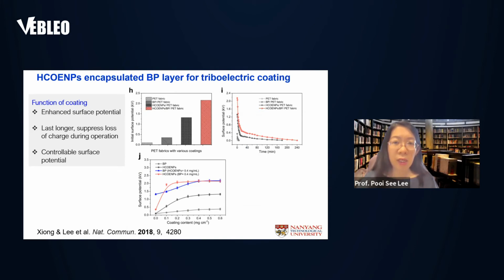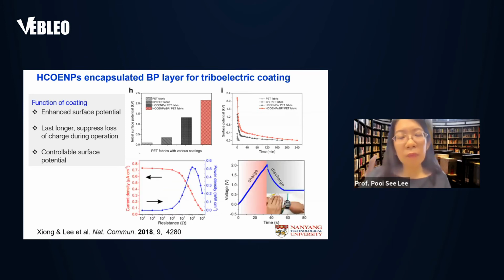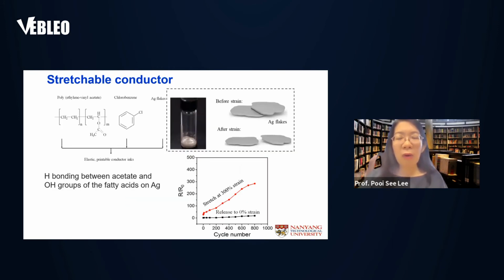So the function of the coating here is basically to enhance the surface potential. Like I explained, the black phosphorus has the ability to trap the charges, and therefore it can work synergistically with the cellulose particle, which leads to an enhanced surface potential, which suppresses the charge loss during the contact separation mode. Controllable surface potential can be achieved based on the amount of coating content as a function of concentration or loading amount, which is tunable as shown here. As a result, the power density is in the range of 0.5 milliwatt per centimeter square, which is very good, which can provide charging to a capacitor and lead to powering up of electronic gadgets just by mechanical tapping.